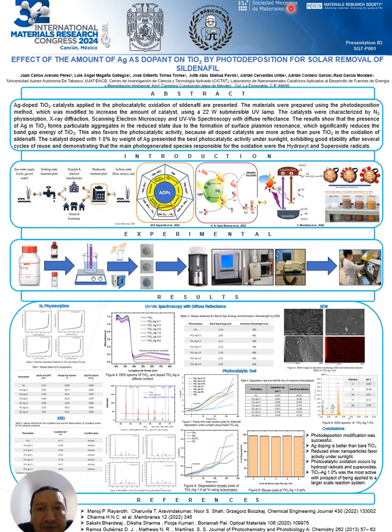The optimum amount of silver doping in titanium dioxide was 1%, since this catalyst was the most active and showed good stability in the consecutive reactions. Hydroxyl and superoxide radicals were shown to be the photogenerated species that are most influential in the oxidation process of sildenafil under sunlight. Thank you very much.